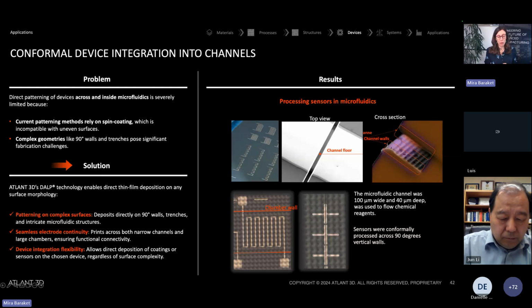These are not compatible with the standard fabrication processes, and with DALP technology, you are able to directly deposit inside those channel floors. The case that I'm showing you here is about microfluidic channels that are 100 micrometers wide and 40 micrometers deep. And we were able to deposit the sensor conformally even across the 90-degree vertical walls.